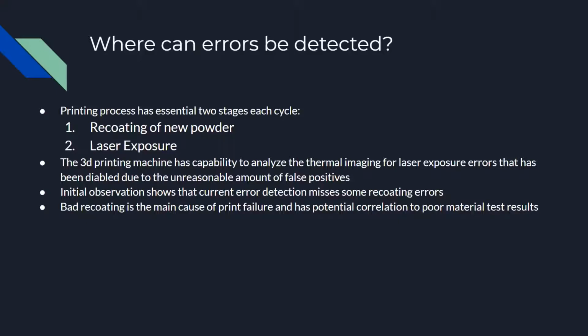The printer has two printing stages. It lays out a new layer of aluminum powder evenly as the material for the next layer of the print. It then exposes the desired area with a high-powered laser to melt the powder and then add the next layer. The printer is extremely accurate when it comes to the laser exposure, so very few print errors or print failures occur in that stage. The recoating, on the other hand, has led to aborted prints and a few cases of part failure.